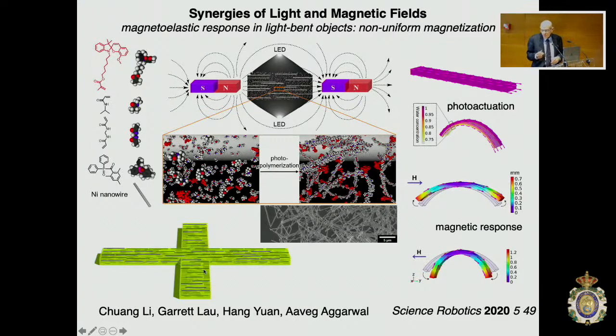My postdoc, who is a phenomenally talented postdoc, just did something very simple. We took the film and he cut with scissors this cross where all the nickel nanowires had been oriented in the magnetic field during polymerization of the monomer of the soft material. Very simple thing. If you put this cross in a magnetic field, the cross doesn't do anything. It just sits there.